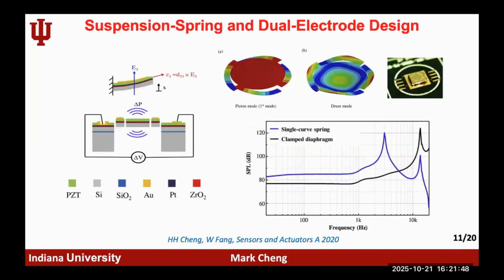Another thing Professor Fang from National Tsing Hua University is trying to do, as a micromachining person, is add more structure to the resonance structure. Instead of just the membrane or the diaphragm, you can couple it with some mechanical structure that introduces a different resonant frequency, and when they couple together, you are hoping to get a good response for the speaker. But again, if you look at what they ended up measuring, those couplings are still too strong, so there's definitely a lot of design that needs to be thought about. They also propose a different driving scheme. Instead of just one electrode, they use multiple, three or four, to try to improve the vibration power as well.